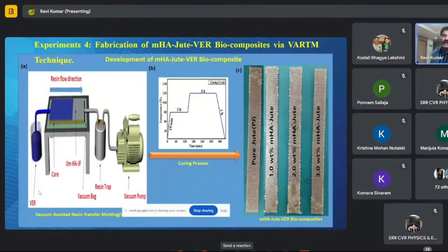And also here, experiment 4, fabrication of MHA jute VER biocomposite via VARTM. VARTM means vacuum assisted resin transfer molding technology, where there is a vinyl ester resin. It was gradually passed through the panel. This is the panel we made with the jute fiber after deposition of MHA. So the resin is flowing in the forward direction because the vacuum is created from this side. So automatically the laminar flow happens on the surface. So the MHA jute fiber composite is formed here. The vacuum bag is attached on the surface, and the excess resin is trapped on the surface. Later, after completion, the panel looks like this.